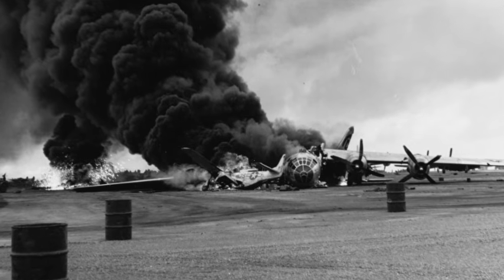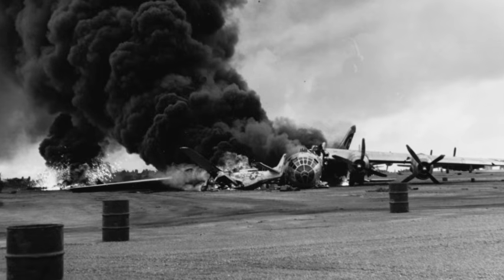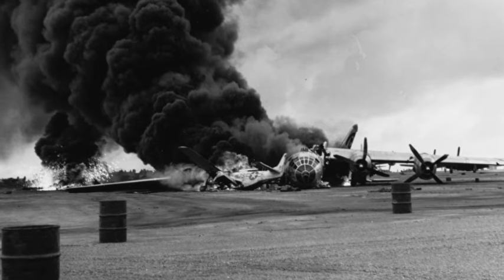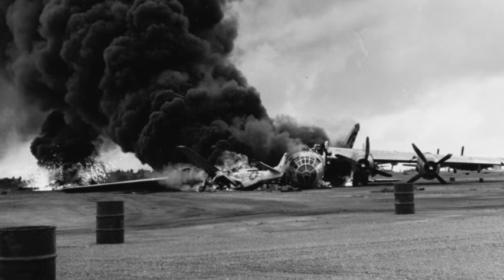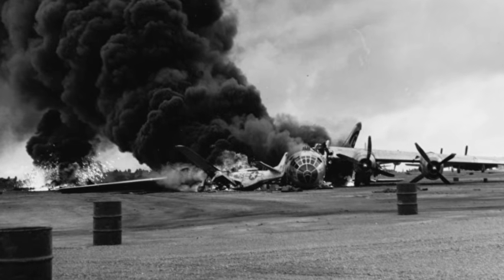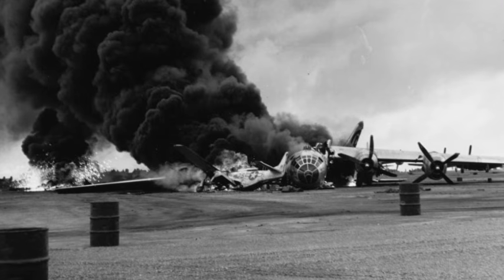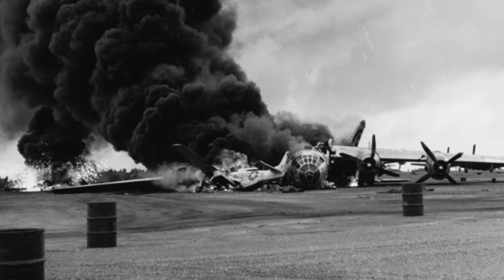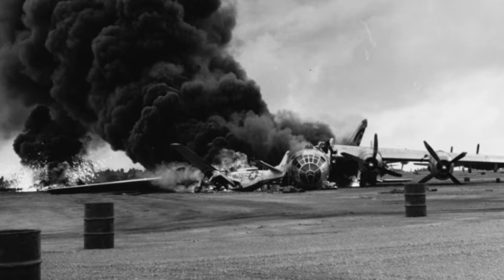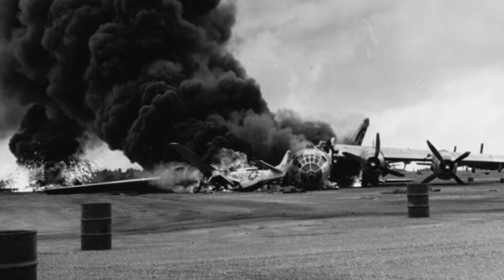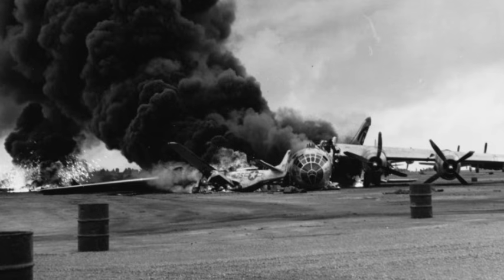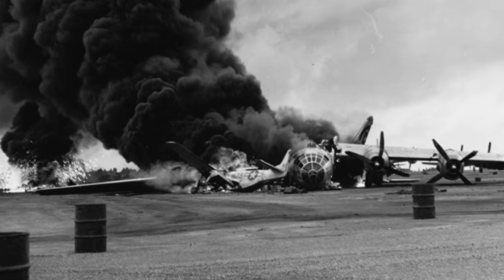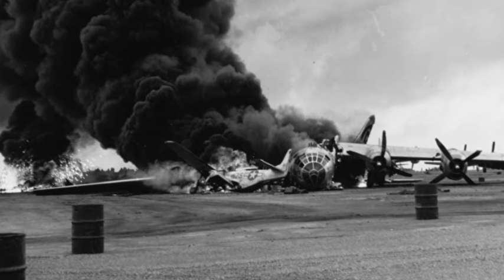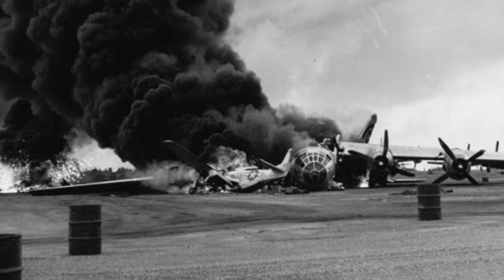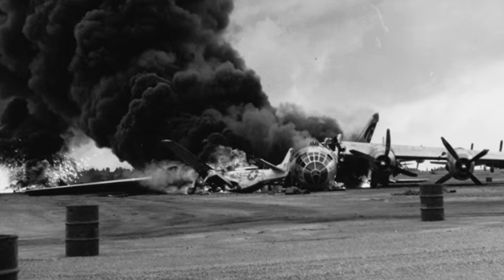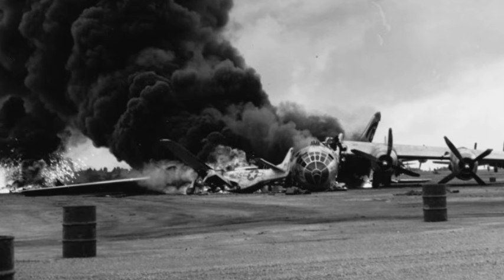The consequences were severe. The engines tended to swallow valves, the exhaust valves overheating and failing, and being drawn into the cylinder, destroying it. The magnesium crankcase, used to save weight, could catch fire, and a magnesium fire burns at a temperature high enough that water makes it worse rather than better, splitting into hydrogen and oxygen that recombine explosively. B-29s were lost to engine fires that burned through the wing spar before the crew could put them down.